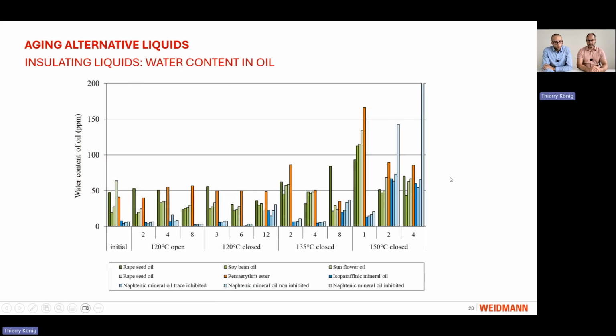So the first results I want to look at are regarding the insulation liquids. And here we see the water content from this experiment. It's a bar diagram, and in green, you can see the vegetable natural esters. In orange is the synthetic ester, and in blue are the 4 types of mineral oil. We have always taken an initial value before the test was started. In here we can see the open and closed system, and both were at 120 degrees, and in here the closed system at 135 and at 150 degrees.